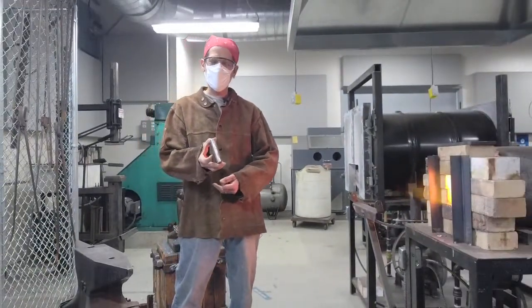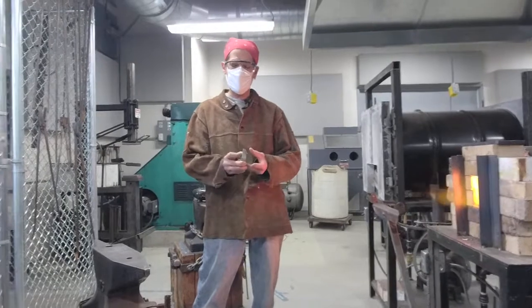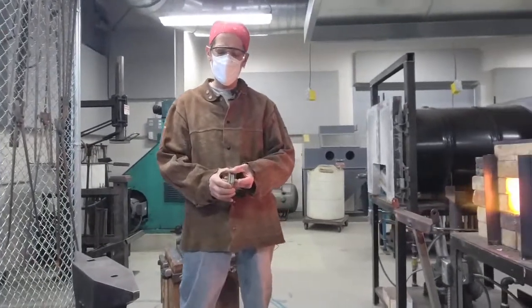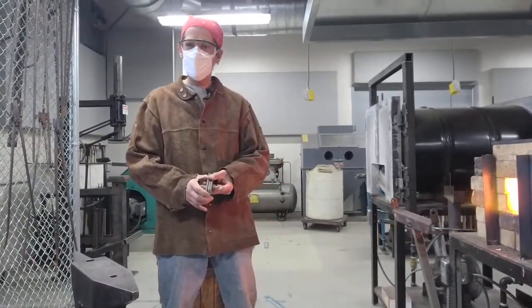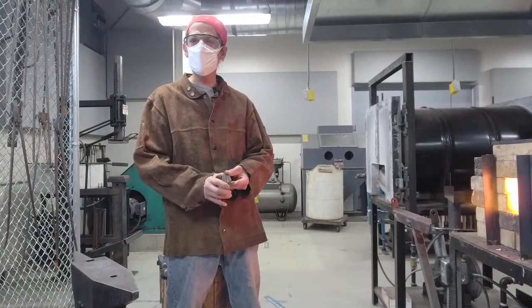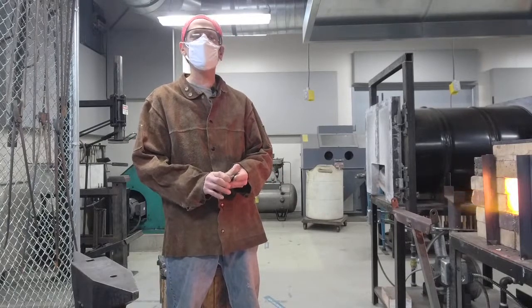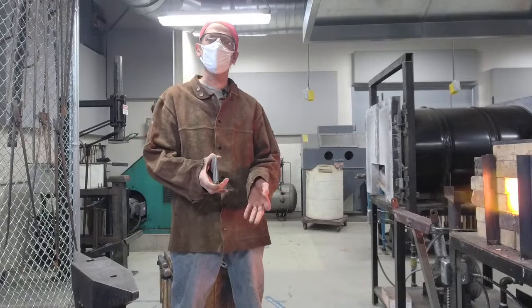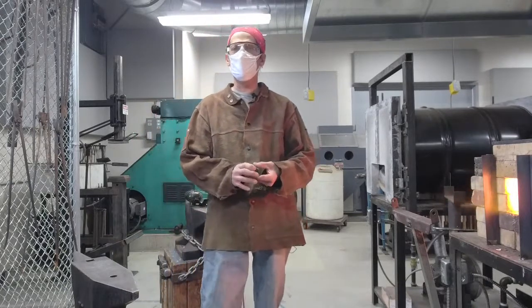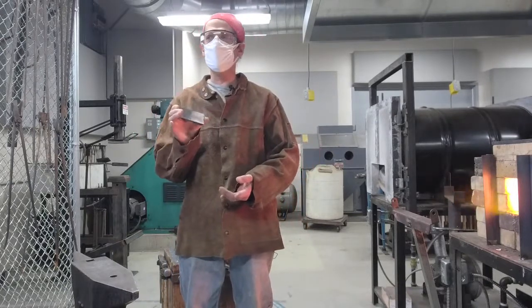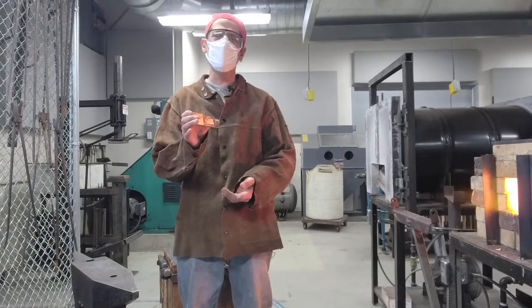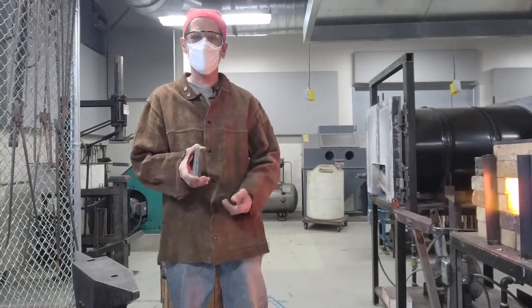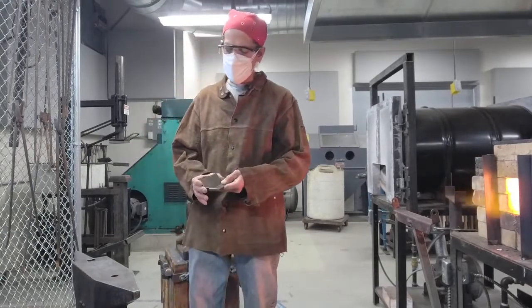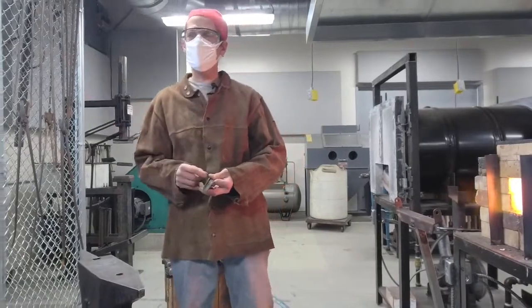Now this is a very small stack. Usually I do 2 to 10 times the size of that, but it would take too long just to heat up a chunk that size for the time we have. So I'm going to do a small billet. I often do small billets like this when I'm testing out a new alloy just to see how it reacts and its working properties. The first thing I need to do is to go over to the sander.